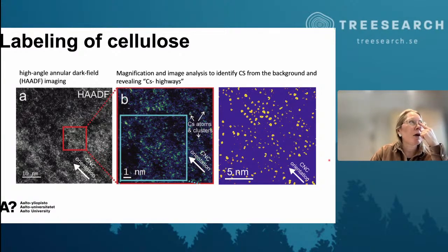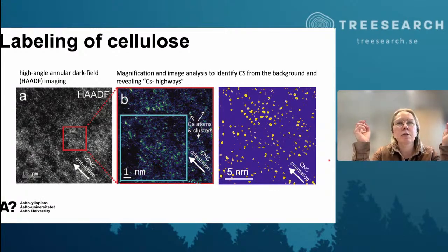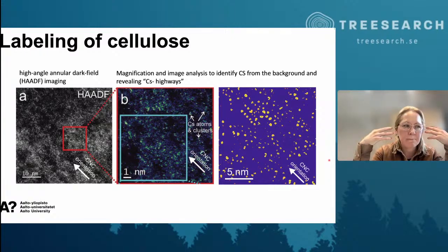And so here, what we should keep in mind when we think about what we can conclude from this is, we have these cellulose nanocrystals. They are sulfated. With our analysis of the sulfur content, we know how much sulfur there is. We can estimate from that how much of the surface, for example, should be covered with the sulfate groups. And in this case, we estimate that it should be approximately 15%. Then we also think about where the sulfate group is. We are thinking that it's in the C6.